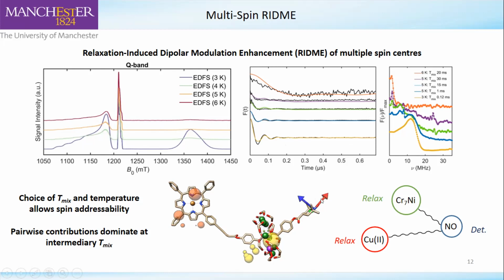But if we raise the temperature a little bit and make our mixing block time even longer, we start to get contributions from the copper spin coming into play. And at 6 Kelvin, we get solely a contribution from the copper spin at a very long T mixing block time. So basically, we can just change the length of our RIDME experiment and play around with the temperature as well to choose which interaction we want to look at.